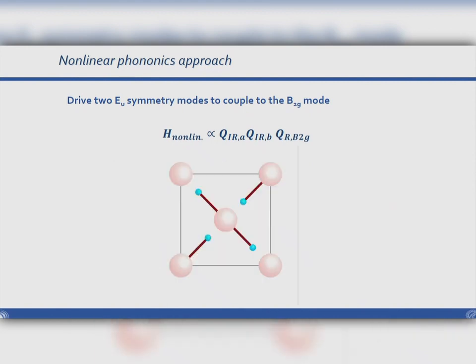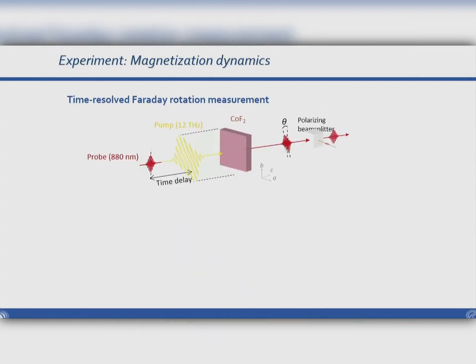Okay, and here's a simulation from Michael Fechner, my DFT colleague that I mentioned at the beginning. As soon as you start oscillating this way, you see that on average, this distance between cobalt and fluoride becomes smaller. This distance also becomes smaller. And then as soon as the atoms stop ringing, these go back to the original position. Okay? So can this indeed now lead to magnetization?